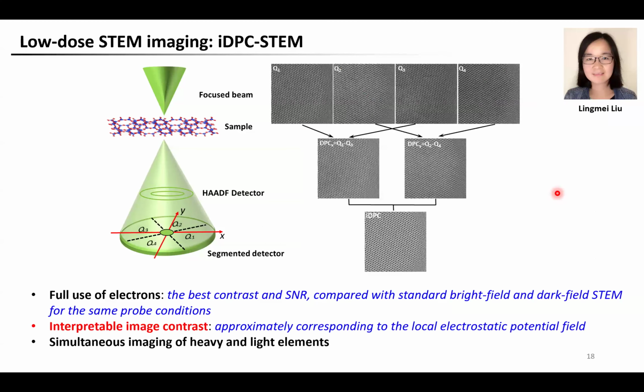Although the ultra-low-dose HRTEM has proven successful in many applications, it typically requires image processing to render the image interpretable. And this image processing not only demands expertise, but is also prone to generating artifacts. So as an alternative, we are also exploring the commercial iDPC-STEM technique for low-dose imaging. Compared to the conventional STEM modes, iDPC has some advantages. For example, it has a higher electron dose efficiency, and it has the ability to image light elements and heavy elements simultaneously. Compared to HRTEM, the iDPC image can be more easily interpreted.